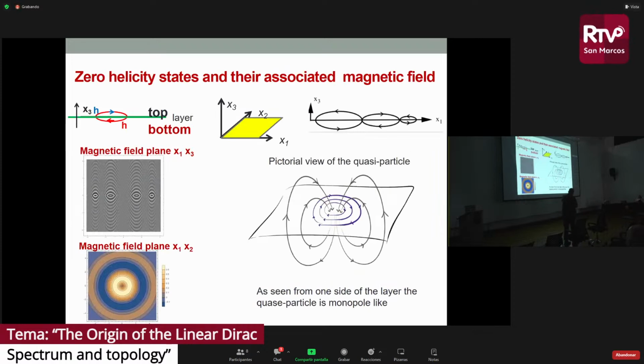In fact, if we compute here, I will just show some brief calculations, just to give you an idea. You have these loops, and you have alternating areas of positive field and negative field if you look from the top, x1, x3. So the best is to hold on to this picture. This is the structure of the quasi-particles in this theory. You have magnetic field loops around a point, and if you look from one side of the layer, what you see is exactly a magnetic monopole.